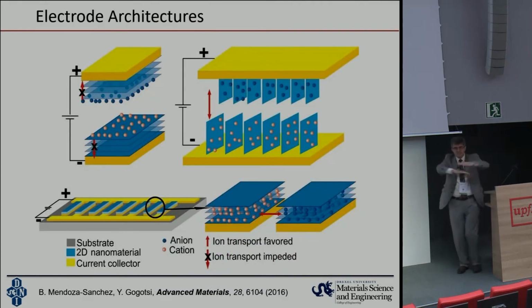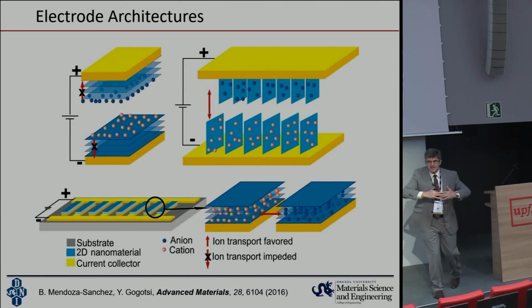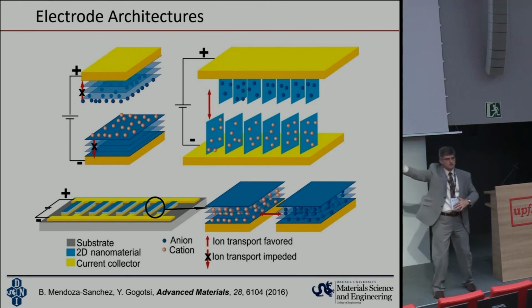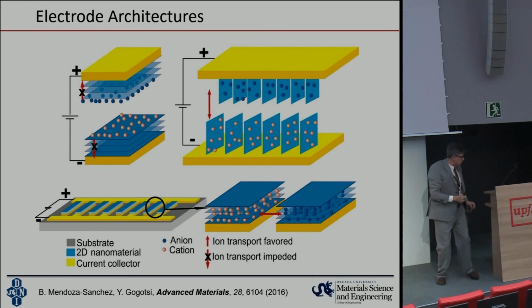But whenever we have flakes aligned horizontally, we cannot build a very thick layer. Not because we cannot build it, we can build it physically. But the diffusion paths will become so long for ions that we will get limited by ionic diffusion.